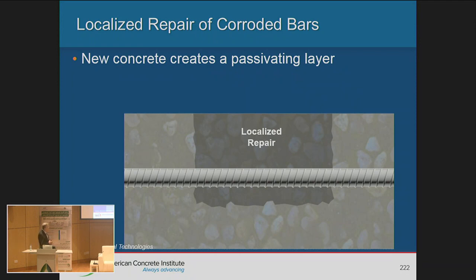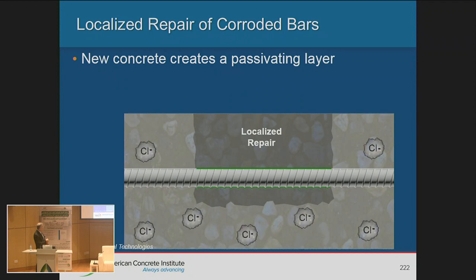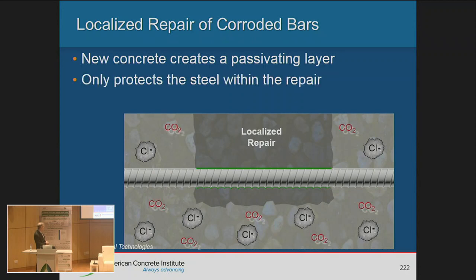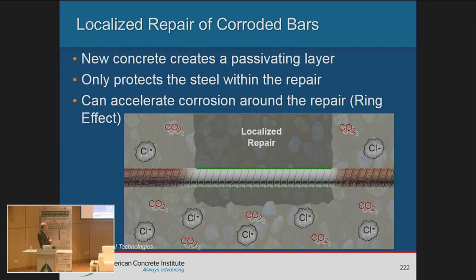So if you look here at this localized repair, for example, the engineer may have found a crack in the concrete, came in, enlarged the area of that concrete, took it out, cleaned it, and put in that patch. What will happen here is you'll get that film or protection layer that we saw earlier this morning. But if you have contamination within the concrete outside that area, because here the concrete now has high pH, but the surrounding concrete is contaminated with chloride or carbonate, that will accelerate the corrosion of the bar outside that area. What you will see on the surface of the concrete are ring cracks. We call it the ring effect, or the halo effect. So there are round cracks around that repair area.